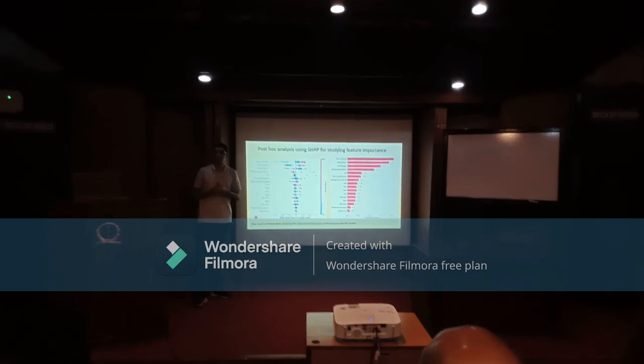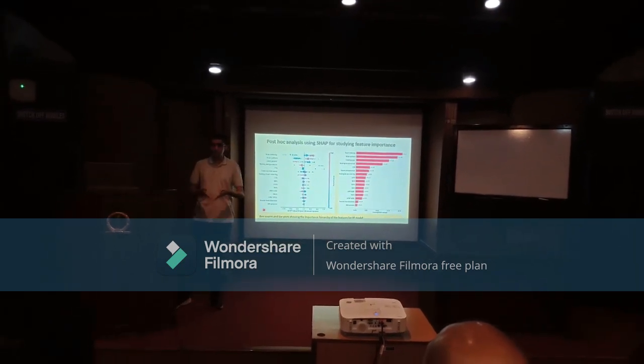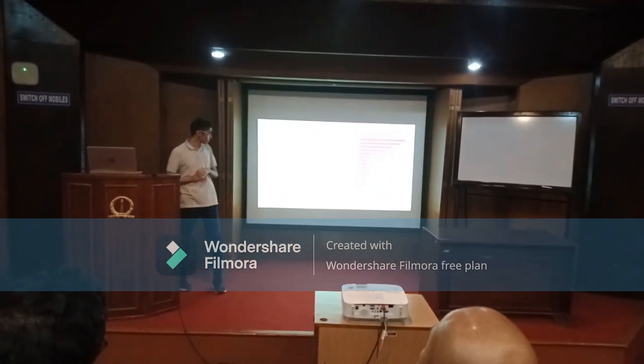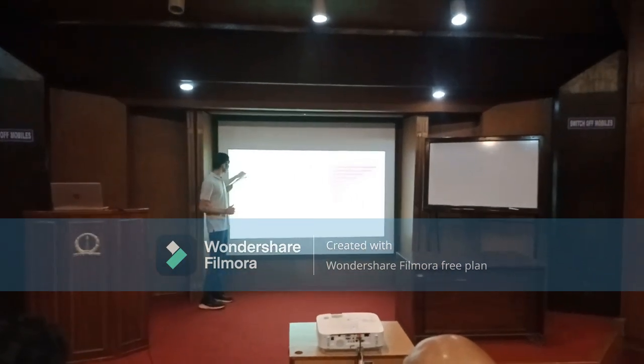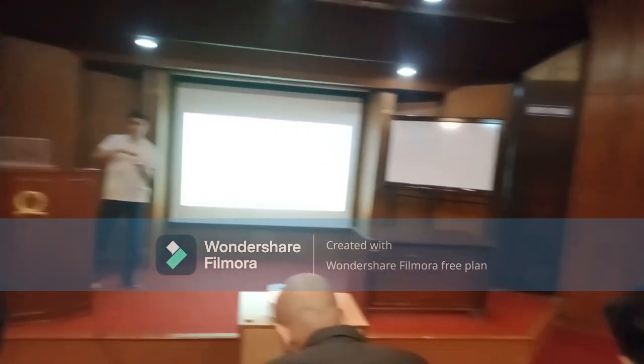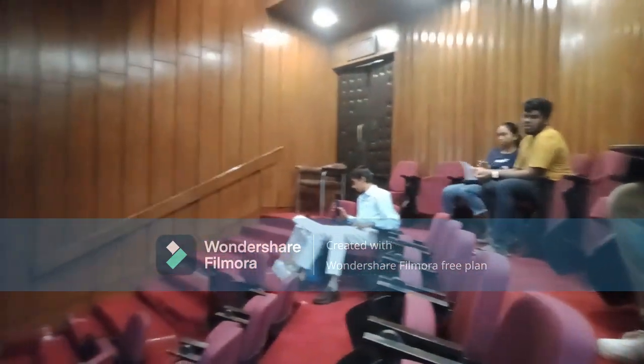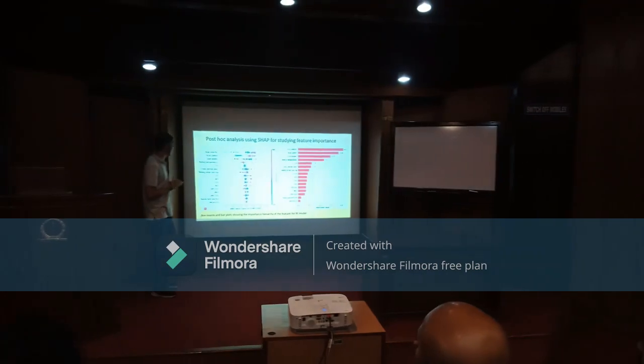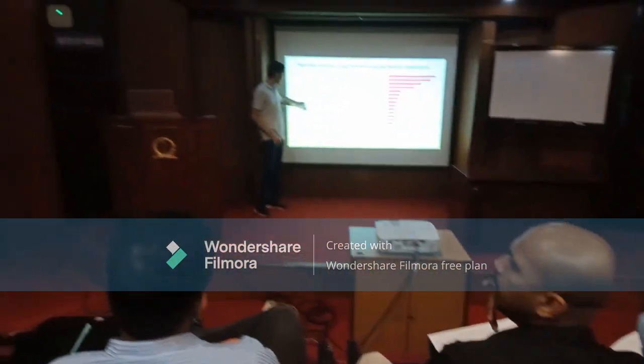A similar kind of explanation will also go for laser power. Higher laser power will mean that we are inputting more heat into the material, and as a result, we have slower solidification, larger grains, and a lower strength value. Similarly, scan pattern also showed a quite significant effect. Scan pattern is basically how the laser is scanning. It can scan in different ways when we look at different layers, so the layer orientations can be different among the layers. That will also have an effect on the final strength. Similarly, the composition also has an effect because of the different sizes that different atoms will have.